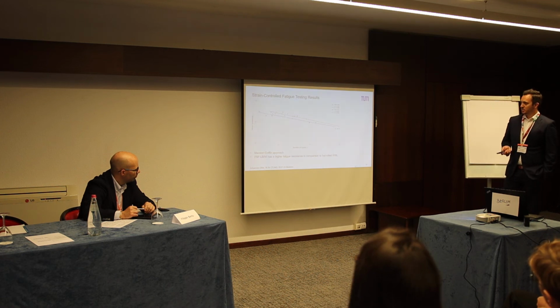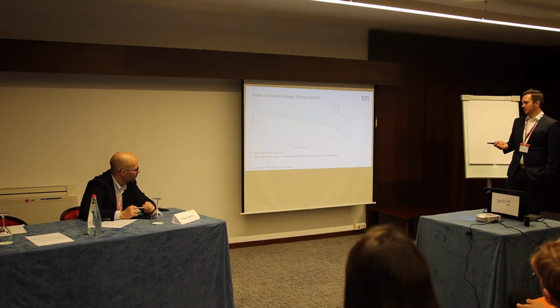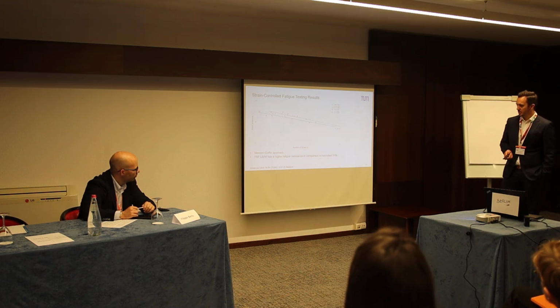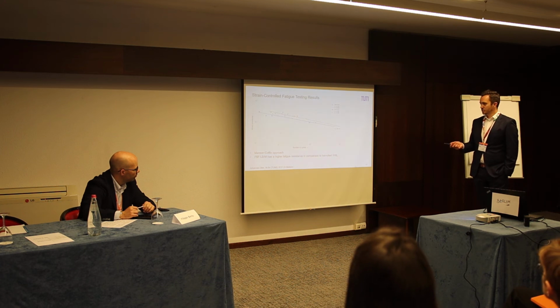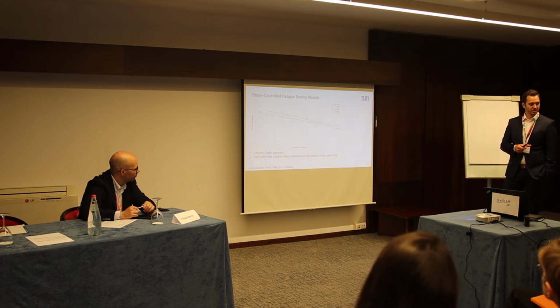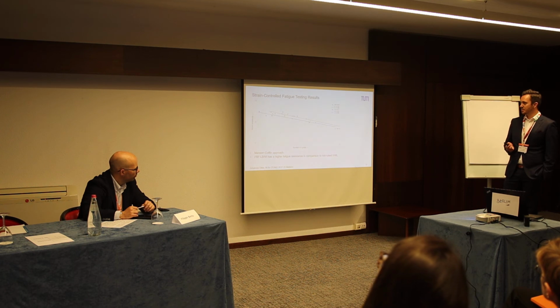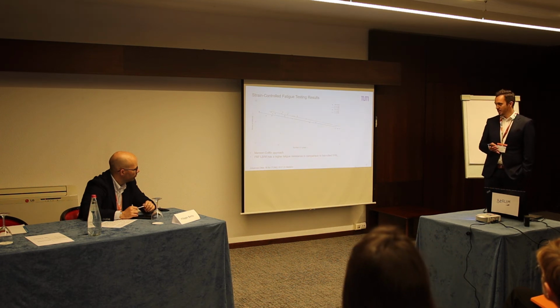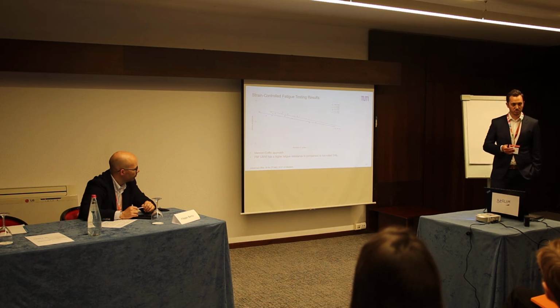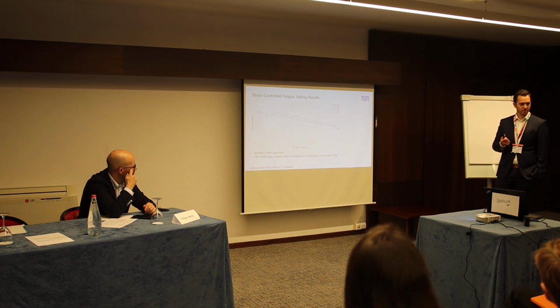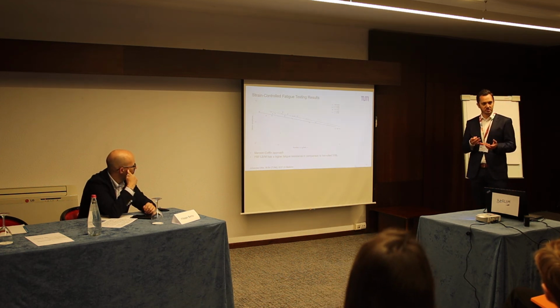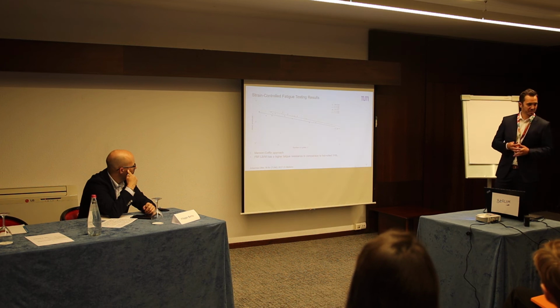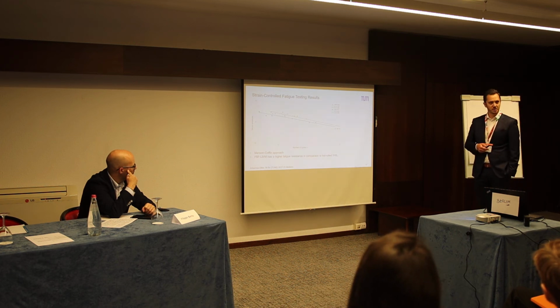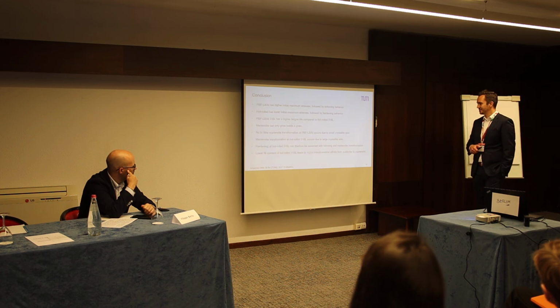So last but not least, I will talk about the strain controlled fatigue testing results in terms of the fatigue life. And here the strain amplitude and the number of cycles is compared. For the curve fit, we use the plastic part of the Manson-Coffin approach, and we can clearly see that the PBF-LB manufactured 316L actually has a better fatigue life compared to the hot roll one. I need to say that we polished the surface of both samples before testing, obviously, to have the same surface roughness at the end. I mean, the professor said earlier that this is also a big influence. We're also investigating that, but I'm not talking about that today.